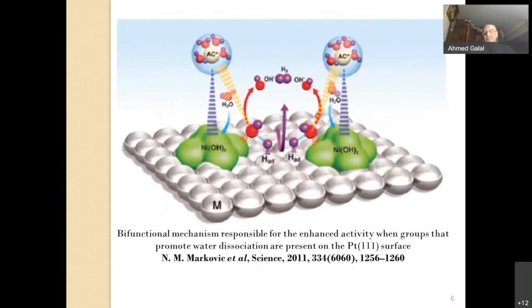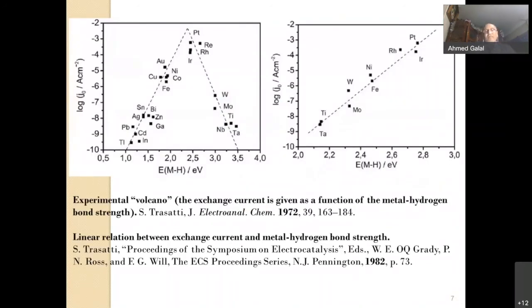The mechanism has also been shown in this particular publication, shown in Science, for the bifunctional mechanism, and some of the speakers have also pointed out this particular issue about the bifunctional mechanism. Of course, one would like to look at what Sergio Trasatti has offered, and in this particular case, it's the famous volcano plot between the energy of the metal binding to hydrogen in electron volts and the current density obtained, and this linear relation can also be deduced by comparing both the theoretical and the experimental work.